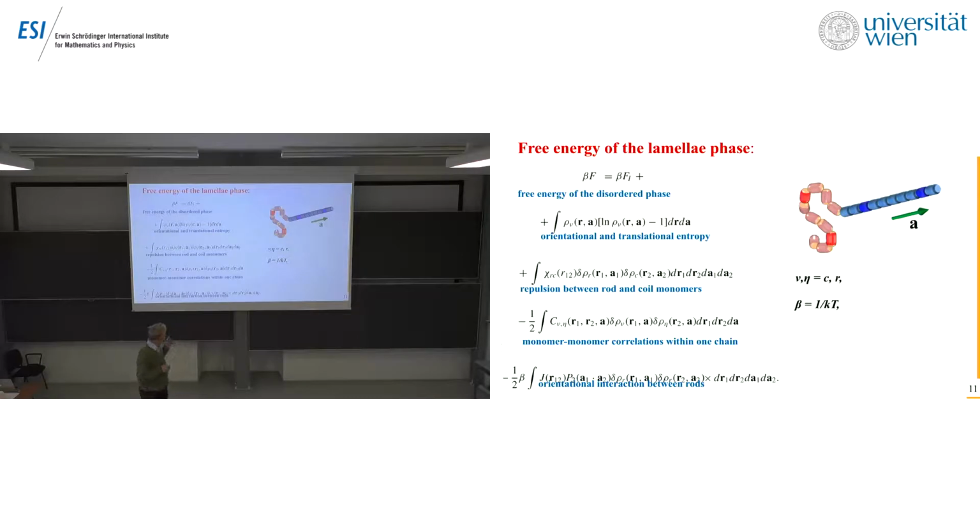And that's not only that I'm not taking it, but I'm trying to follow the existing polymer theory, which just tries to make as simple a model as possible, because there are plenty of other things. For example, this Maier-Saupe interaction is, frankly speaking, very much incorrect, because the real interaction between rods is not only a coupling between long axes. It involves the orientation of the rod with respect to the intermolecular vector, right?